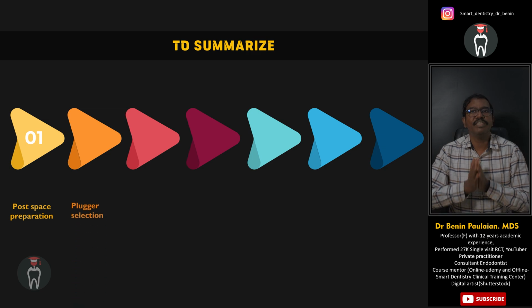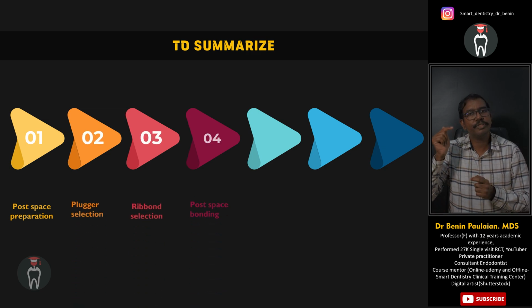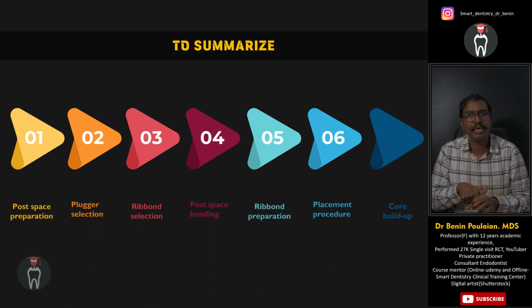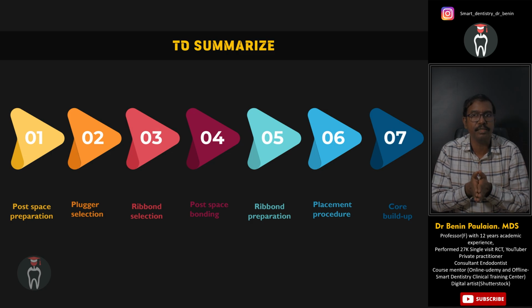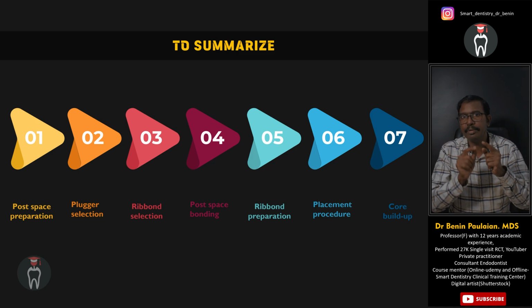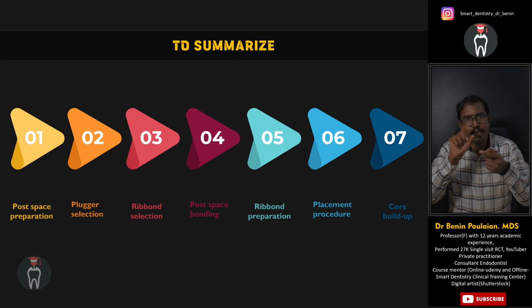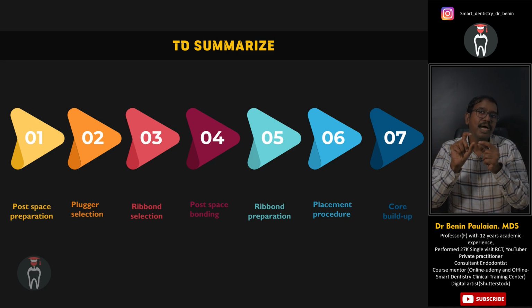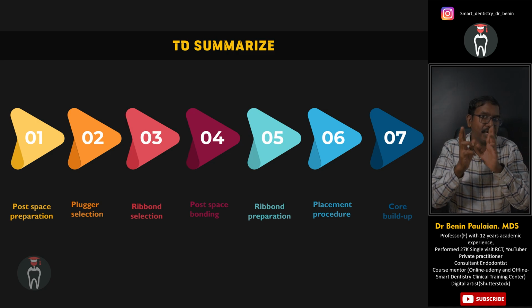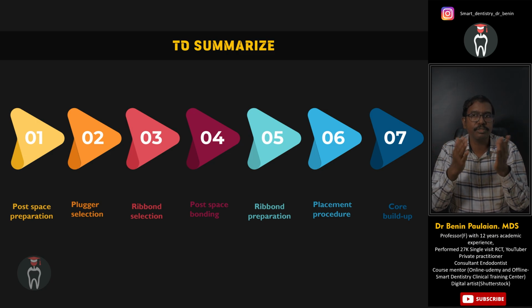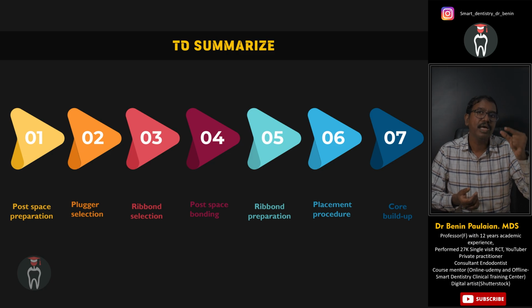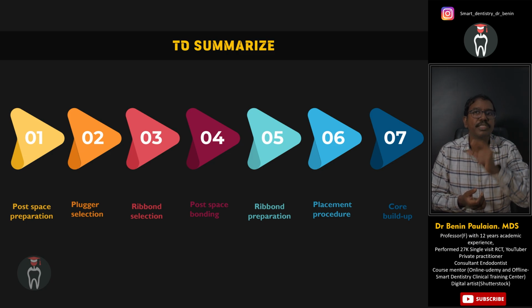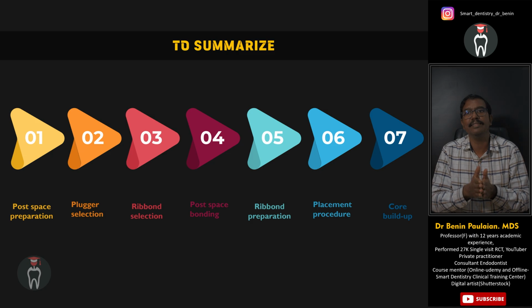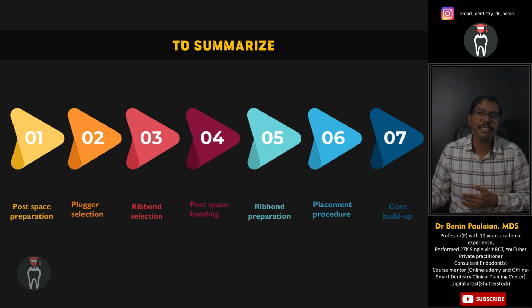To summarize this, first you have to prepare the post space. Then you choose a plugger in order to measure. Make sure the plugger reaches the full length of the post space that you have prepared. Then you have to choose the ribbon material. Choose the length. In this example, you know the 10 millimeter post space for 2 layers, so 20 millimeters, and 2 millimeters of excess for both the strings, so 4 millimeters, so 24 millimeters. You can choose the width of your choice, 2 millimeter, 3 millimeter, or 4 millimeter. Cut it, and then you have to prepare the post space bonding.